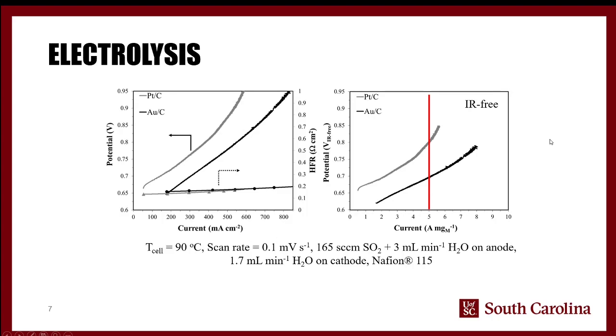And then the electrolysis itself, what we find is that similarly to the rotating disc electrode, the gold had higher current density at lower potentials, we see the exact same thing. So this gray trace here is platinum, the black one here is gold. You can see that, pick 0.5 amp per square centimeter, the gold on carbon hits that at roughly 0.77, maybe 0.76. Platinum doesn't hit that until about 0.86 to 0.87. So we're looking at somewhere in the neighborhood of a 100 millivolt difference. And in electrocatalysis, that's a huge difference.